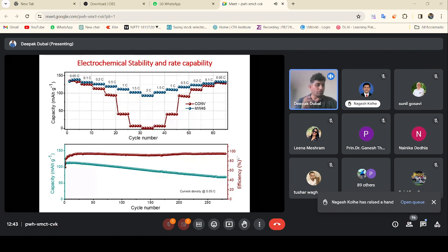So rate performance, this is very interesting to see, the rate performance of the materials synthesized through the microwave process is really very high. So you can see here that with respect to C rate, like applied current density, the specific capacity is still maintained, while with the conventional method, the specific capacity is fading very quickly with respect to applied current density.